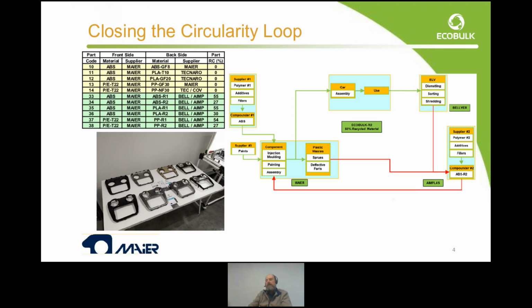The pellets we got from Einplast by using a standard extrusion compounding process were resent to Maier to use as raw material to produce a new version of the same part in the same process by injection molding and painting. So finally, we got three different versions of each combination of material of the same part, just to check and to quantify how much recycled content we can use on the same part, and what the difference is from an ABS to a PP or PLA version.